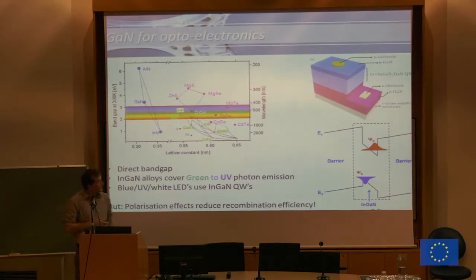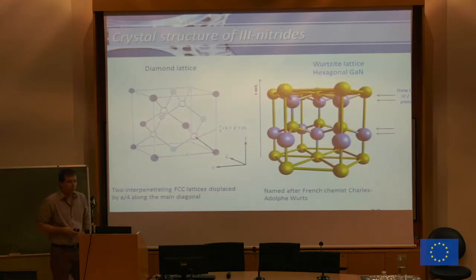And one of the things that people noticed very quickly was that in order to have this very highly efficient emission, you needed to make the quantum wells very thin, so only 2 to 3 nanometers. And the reason for that is that if you look at the band diagram, it seems that the wave functions for the holes and the electrons are spatially separated because of this built-in polarization effect. So it was really shown in practice that there was polarization in the system and that it had some negative effects. So we turn to polarization.